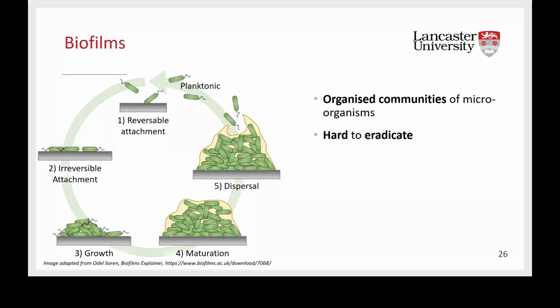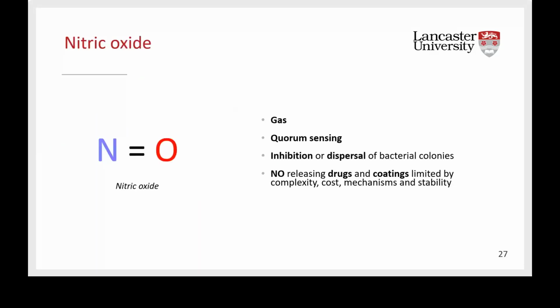The fact is that once bacteria reach a surface, they start growing, forming an organized community called the biofilm. And the biofilm is protected by a polymeric matrix, which makes it extremely difficult to eradicate. So most of the biofilms actually have antibiotic resistance. But we have an ally against this biofilm. It's called nitric oxide. Nitric oxide is a gas that can mess with quorum sensing of bacteria. This can cause dispersion of already formed bacteria colonies or can inhibit the formation of the colonies themselves.